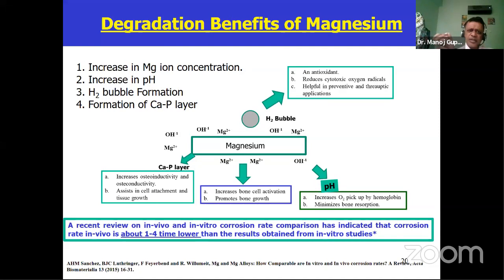Now, if you look from a different perspective, there are a lot of degradation benefits of magnesium - four things you can expect when magnesium degrades. The first is an increase in magnesium ion concentration, which increases bone cell activation and promotes bone growth. It also leads to an increase in pH because OH-minus ions are released, which increases oxygen pickup by hemoglobin and minimizes bone resorption. Hydrogen bubble formation - hydrogen is an antioxidant, it reduces cytotoxic oxygen radicals and so on. And the formation of an apatite layer, or CAP layer, increases osteoconductivity and assists in cell attachment and tissue growth.